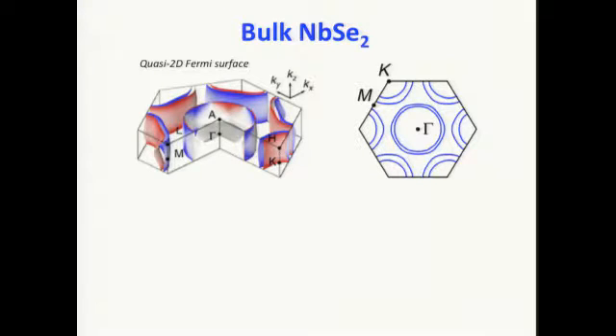A famous example in this class of metals is niobium diselenide. Here I illustrate its three-dimensional Fermi surface. If you look from the top down, it looks something like this, with a Fermi surface centered at the gamma point, and also two other sheets at the K and K prime points of the Brillouin zone. And it's quasi-two-dimensional with very weak interlayer interaction, so that it gives rise to this cylinder-like Fermi surface in the 3D structure.